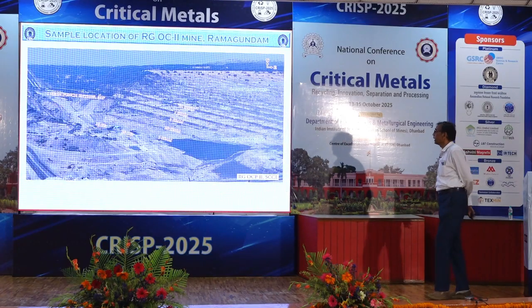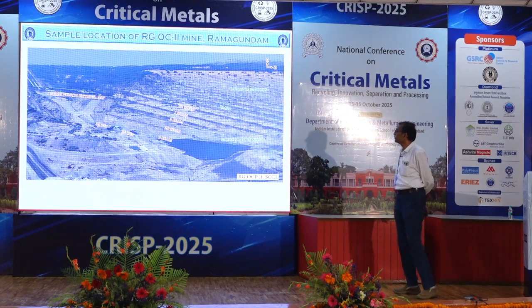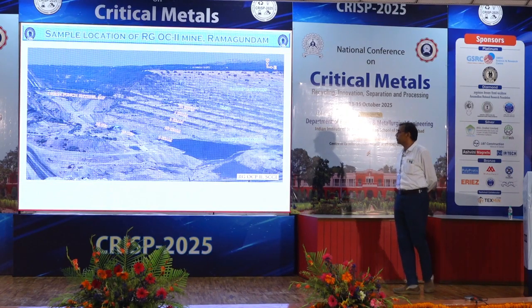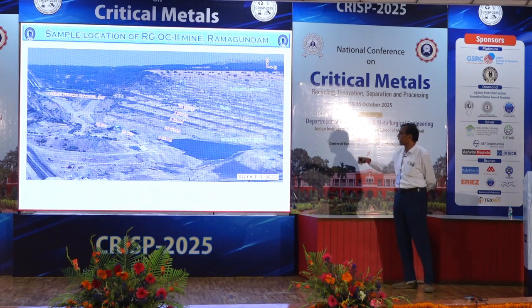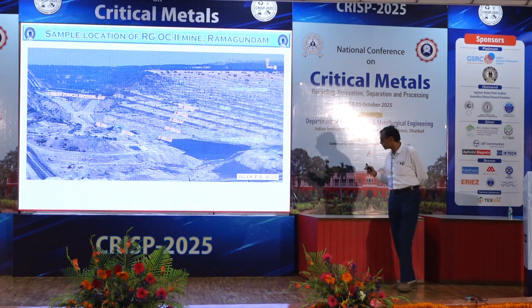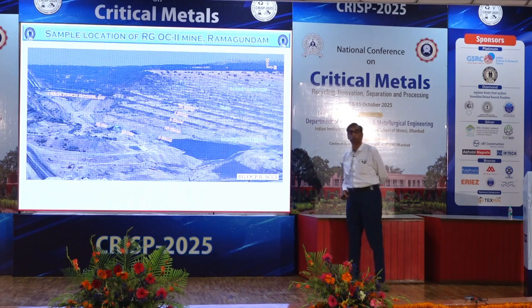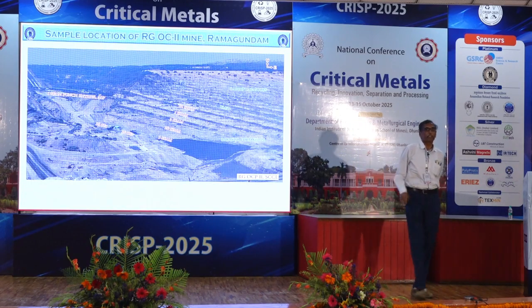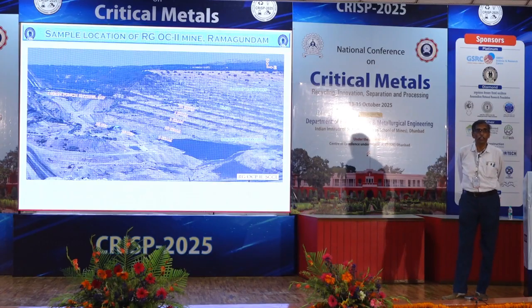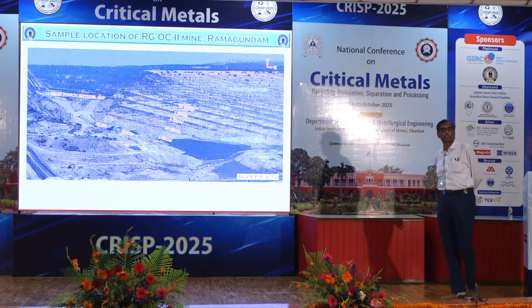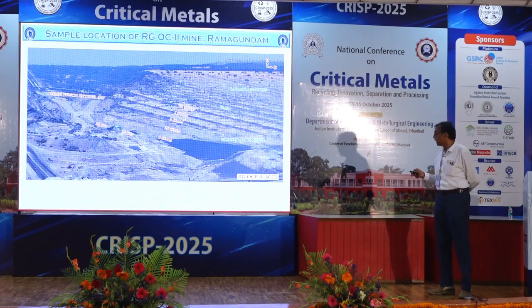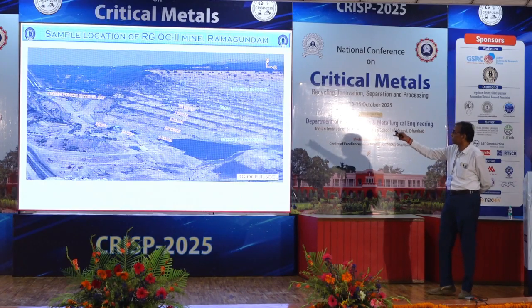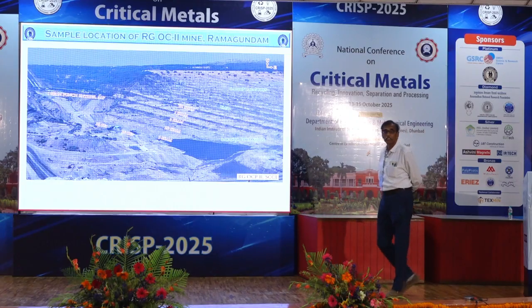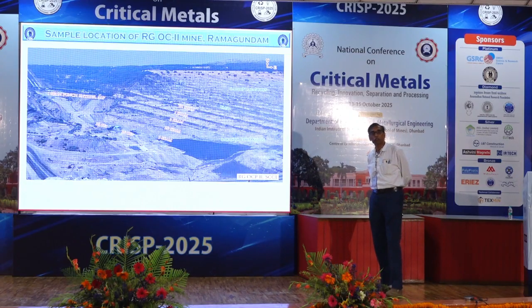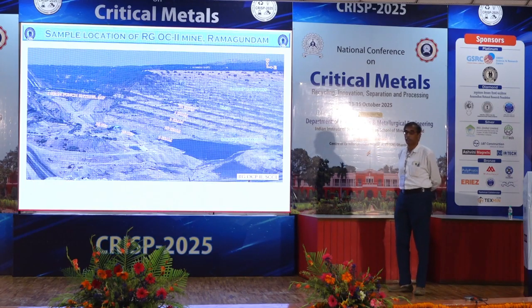This is a typical view of an open cast mine. You can see the order of seams from bottom measure to Barakar. Then there is a prominent band, the clay horizon, which also contains more REs than the other mineral seams. At the same time, the topmost seam 1A1 contains at least 50 to 100 ppm more than any other place in the downward seams.